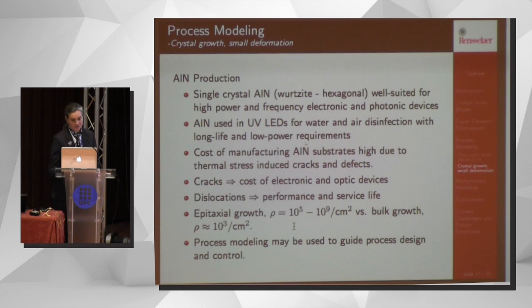However, the cost of manufacturing aluminum nitride is really high still. And that's mainly because there are two main competing methods to make it, an epitaxial growth, but the epitaxial growth has a high dislocation density versus the bulk growth. My colleagues at Crystal IS have developed this sublimation process where they get a much lower dislocation density on the order of 10 to the third per centimeter squared. So it's very low dislocation density, which gives a very long service life and also excellent performance.